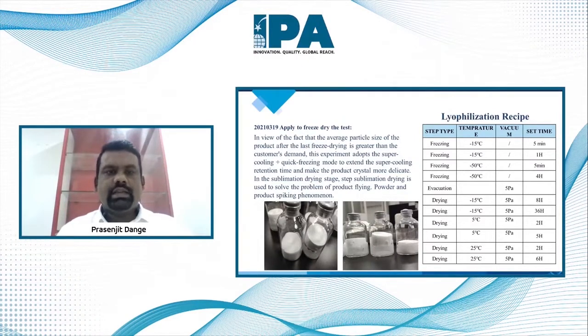So in the next cycle, we have adapted supercooling and quick freezing mode, which helps in retention time and makes the product crystal finer and more delicate. So we applied this new recipe, where the freezing was done at minus 15 and also went much deeper to minus 50 as well. And the whole time was even a little longer.